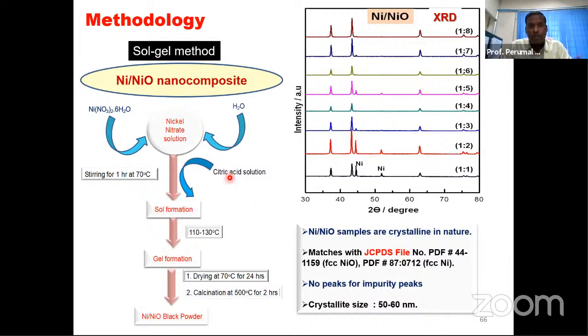Okay, so you can also distinguish composites or phases. For example, one of my students has prepared a nanocomposite consisting of nickel and nickel oxide by following this procedure. He varied the concentration of nickel nitrate, from 1:8 to 1:1, and X-ray diffraction was taken. When the ratio of citrate and nickel nitrate is 1:8, you get one pattern. If you change it, you get both nickel oxide and nickel. No other technique will give you such clear information. You know the presence of nickel and nickel oxide clearly by using powder X-ray diffraction.